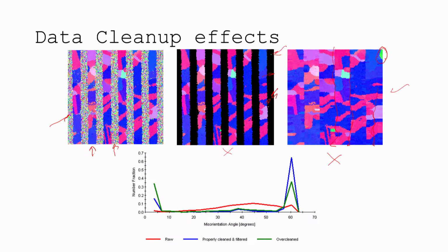If you have a nice, fully dense material that you don't expect any holes in, maybe you're just going to have a few missing points on the boundary, then it's okay to dilate and clean it up. If it's completely crap to begin with, go get better data, right? Don't do a cleanup and try and clean up some really bad data. But cleanup has to have some strategy, like dilation is one method, but we have to define criteria for cleanup.